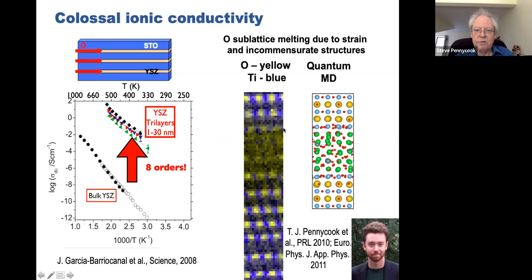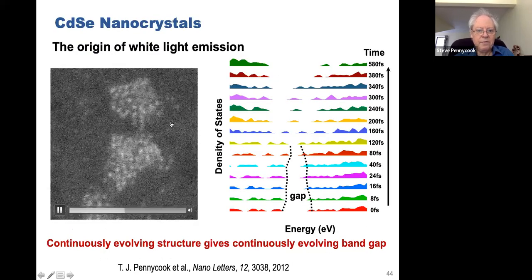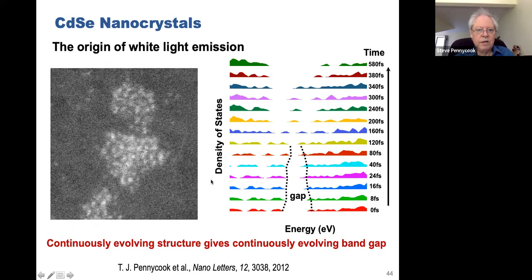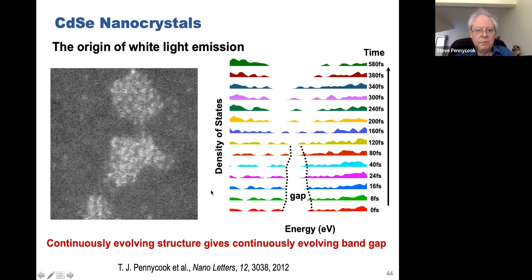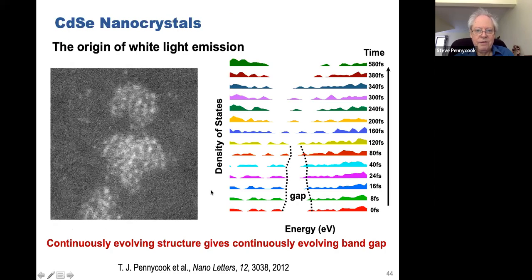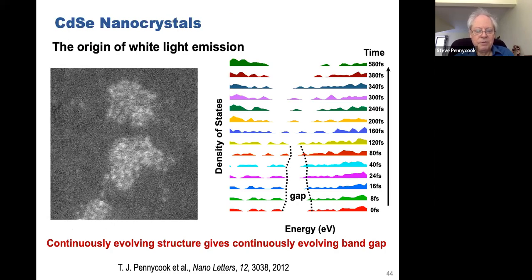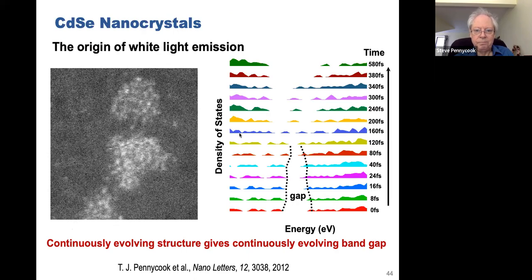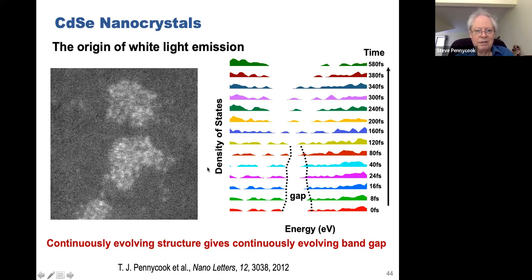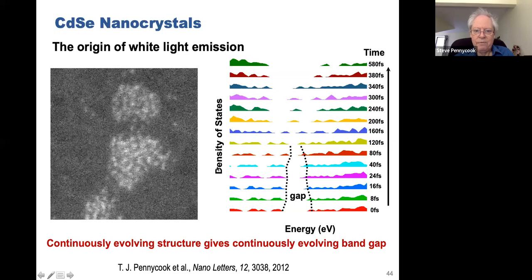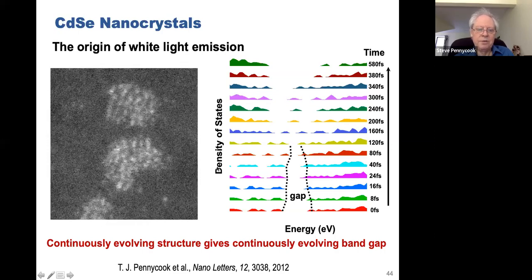And he also went on the UltraSTEM. You could see mapping oxygen here in yellow. It kind of washes out. Looks very like a liquid in the thin YSZ layer. Well, another problem out of Vanderbilt was these white light nanocrystals. They discovered that when they got small enough, instead of having a fixed blue, they were aiming for a nice deep blue, what happened? They got white emission, even from individual nanocrystals.